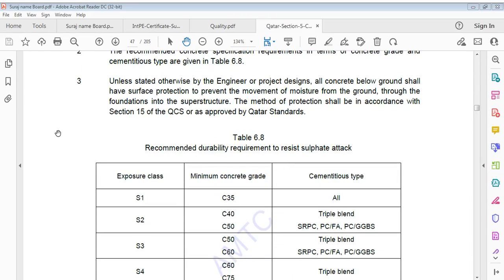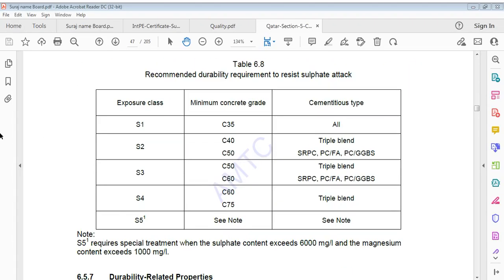Unless stated otherwise by the engineer or project designs, all concrete below ground shall have surface protection to prevent movement of moisture from ground through foundations into the superstructure. Method of protection shall be in accordance with other standards. Now, the recommended durability requirement to resist sulfate attack: there are 5 classes, S1 to S5. S5 requires special treatment when sulfate content exceeds 6000 mg per liter and magnesium content exceeds 1000 mg per liter.